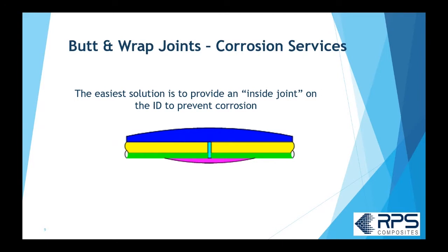It's really only practical on larger pipe, typically 24 inch and larger, or maybe 8, 10, and 12 inch if I could reach in close to the edge. So for example, if I was laminating a flange onto an elbow, I might be able to reach in and get at that inside joint, but it's really only where accessible.